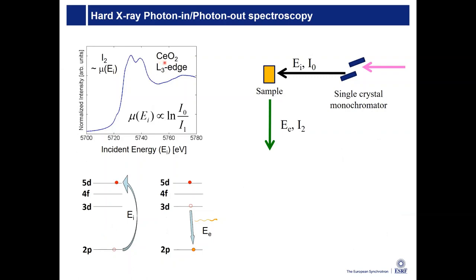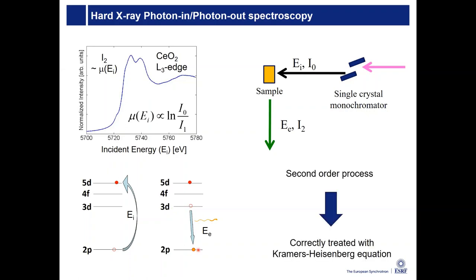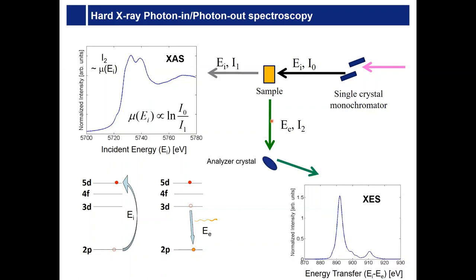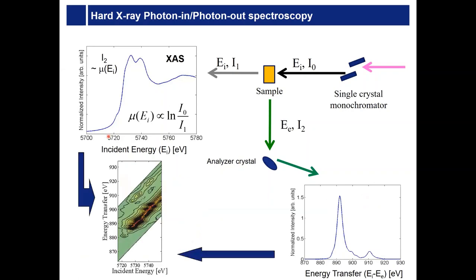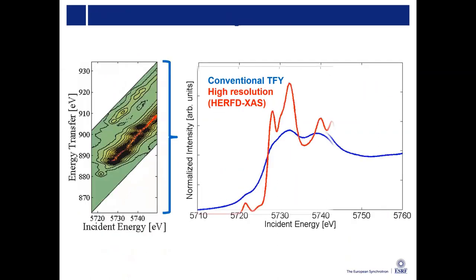So cerium is a rare earth. 5d levels are unoccupied. So if you measure an L-edge spectrum, you excite 2p to 5d, and then you can observe a 3d electron going down to 2p. The second order process has to be described with this Kramers-Heisenberg equation that I showed you before. Now I analyze not only the incoming energy but also the scattered energy, the fluorescence energy, and I get two spectra, this spectrum and this spectrum. I can combine the two spectra and I get the so-called RIXS plane, with the energy of the incoming beam shown here, and the energy of the outgoing X-rays shown here. So I scan both monochromators and get a two-dimensional intensity distribution.